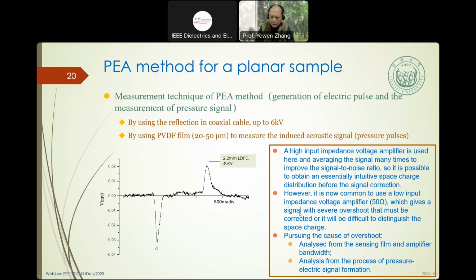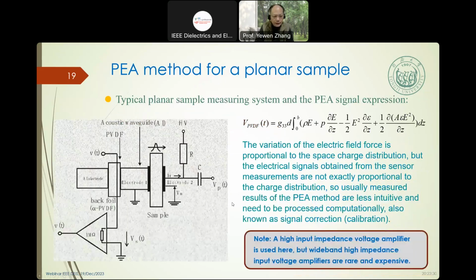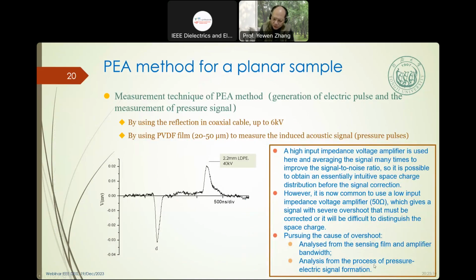So it gets a signal with several overshoots, must be corrected, with difficulty to distinguish the space charge. Possible causes of the overshoot are analyzed: the sensor film and the amplifier bandwidth. So it means we analyze this bandwidth. Another one is to analyze the pressure-electric signal formation.